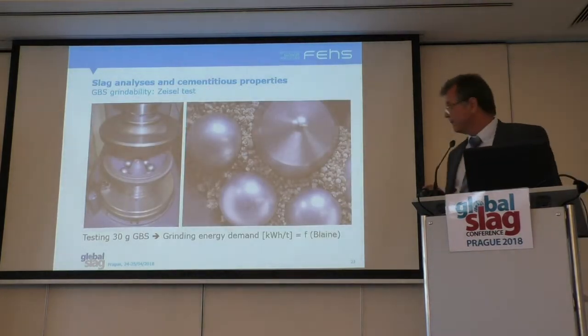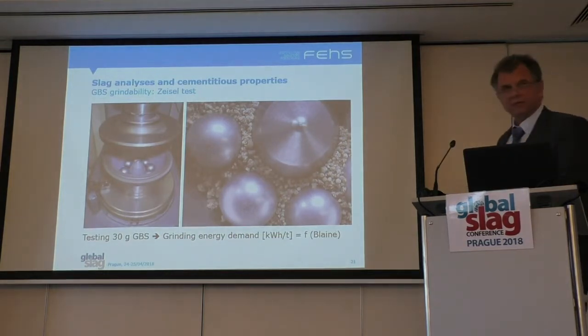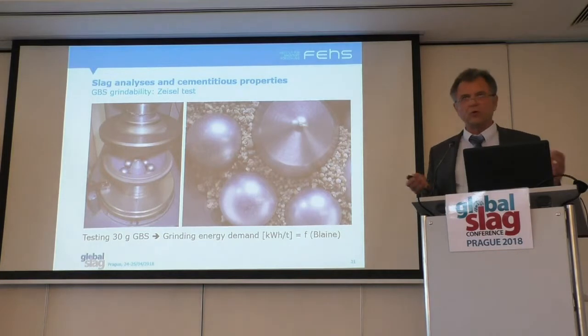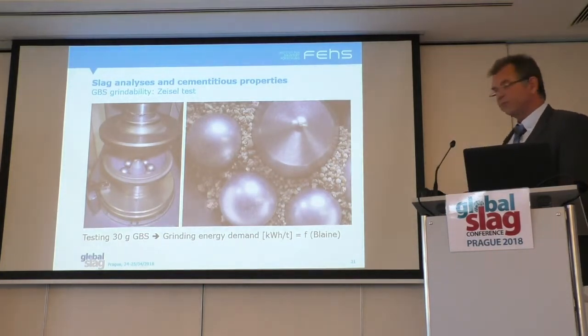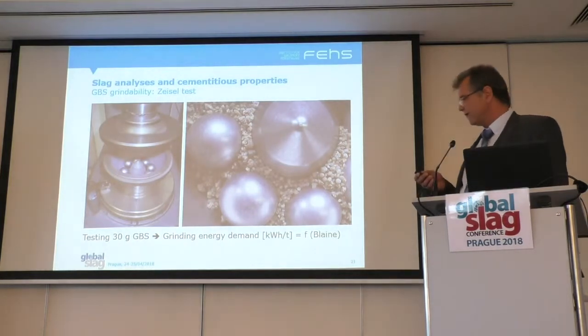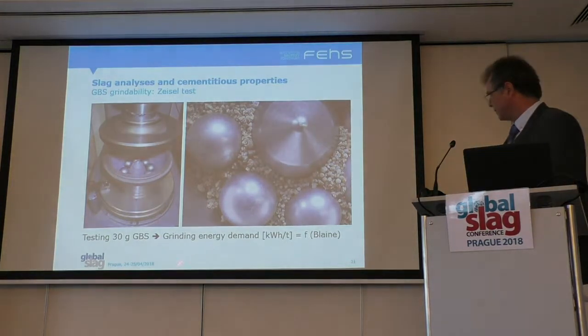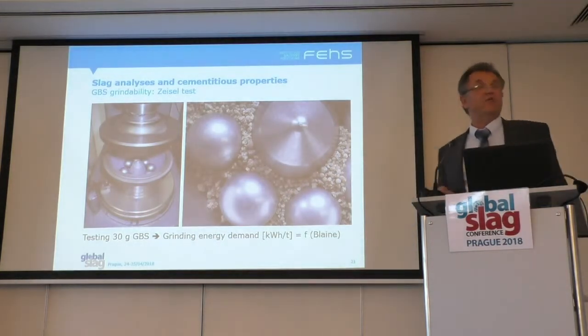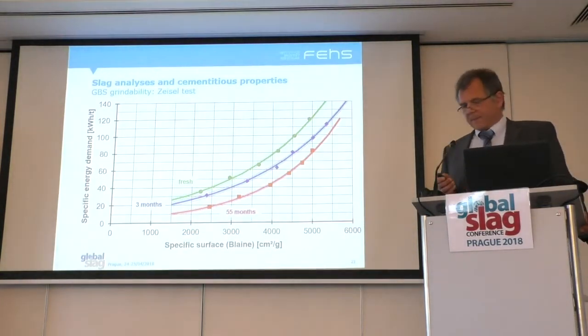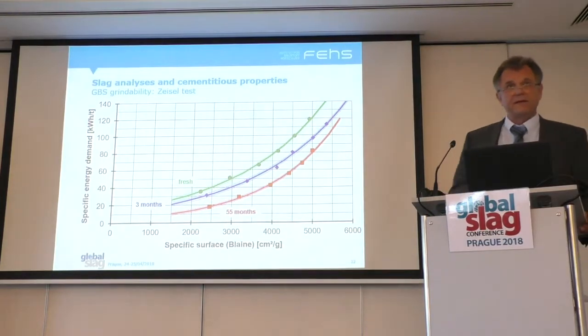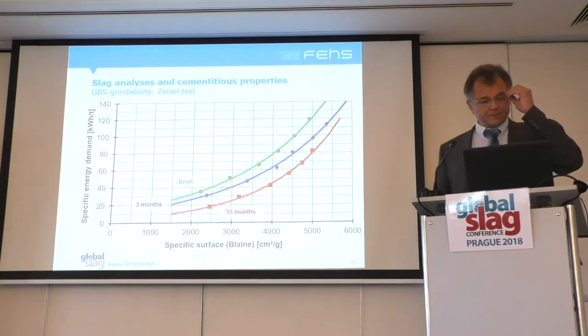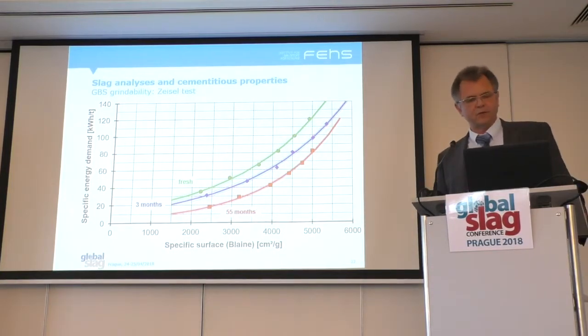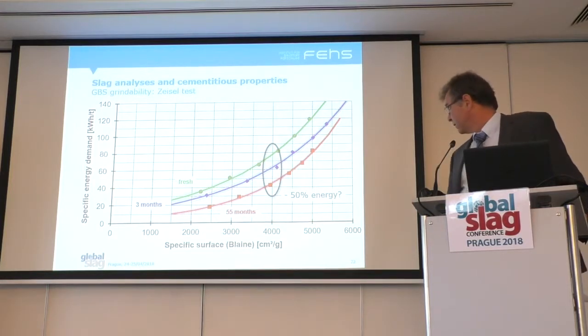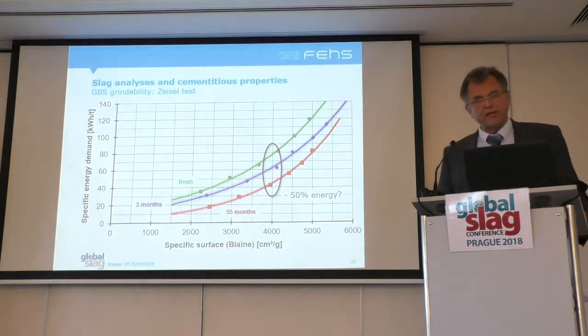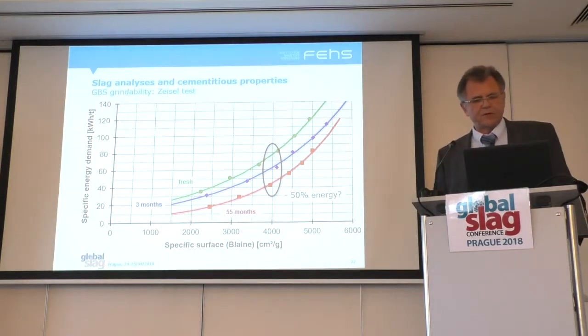Grindability. We test the grindability in the institute with a so-called Zeisel test. It's a small closed ball mill using 30 grams of material, and as a result you get a curve of grinding energy demand in kilowatt hours per ton depending on the Blaine value. And when we measured fresh slags and stored slags, we found that according to the Zeisel test method and according to the Blaine value, it would be very nice at 4000 Blaine, which is a typical cementitious fineness. We need only 50% of grinding energy.